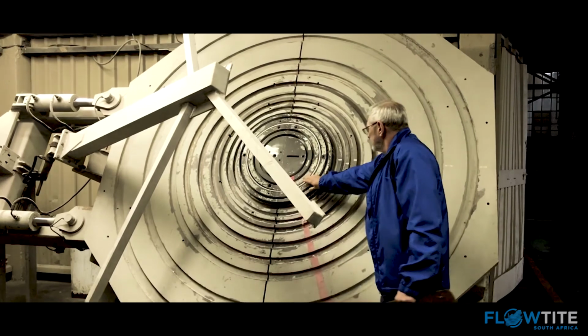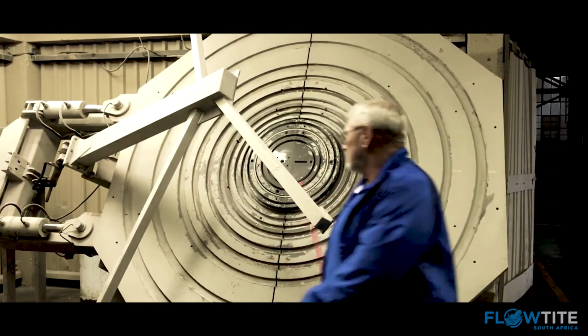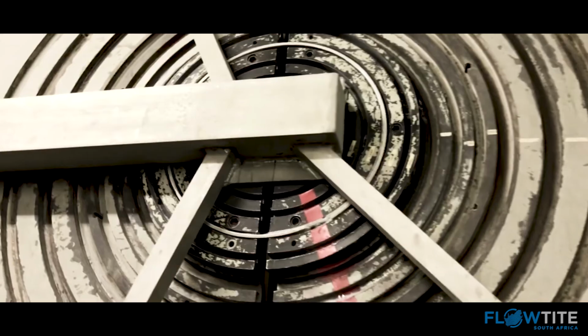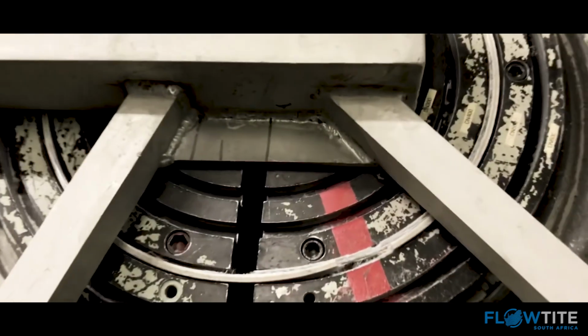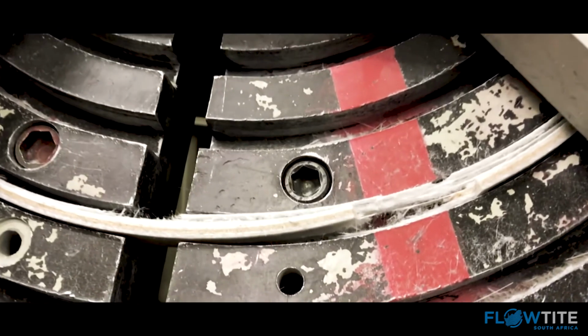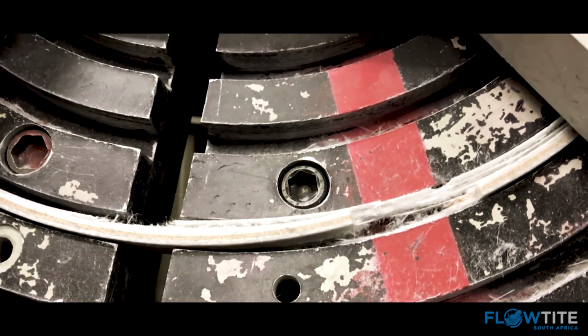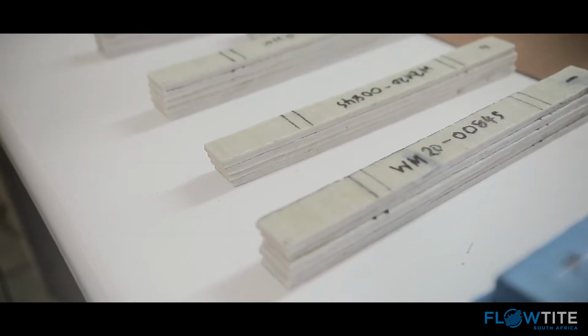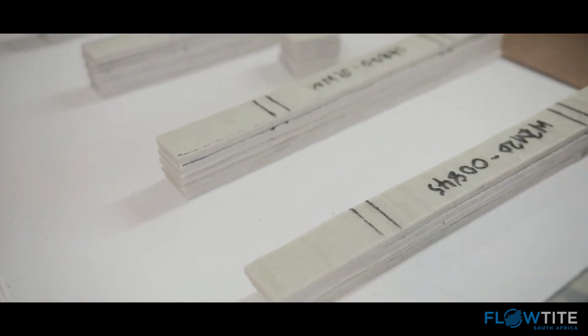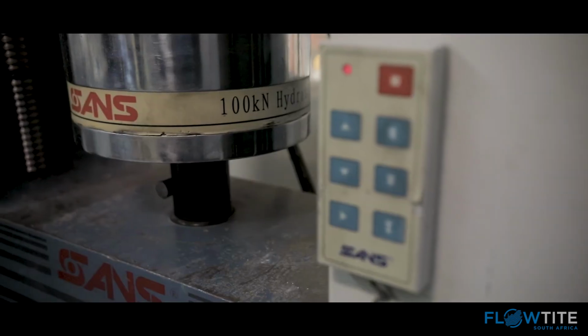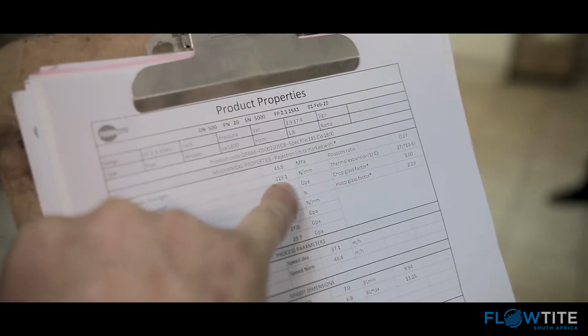We conduct two tensile tests on the pipe. The first one is the hoop tensile. Here, we take a ring sample or slice of the pipe and pull the pipe outward to test the amount of Newton per millimeter it will take to break the pipe. This is then recorded and sampled against the original specification. The second tensile test is taken in the longitudinal section of the pipe and once again pulled until it breaks, to test the newtons per millimeter until the pipe gives away, and is then recorded and compared to the original design specification.